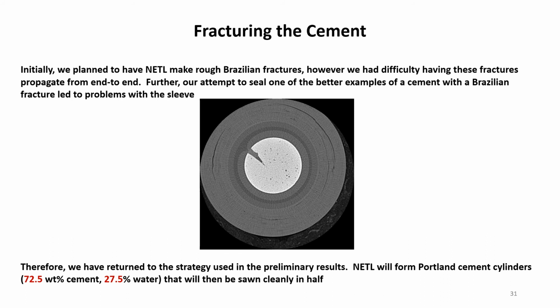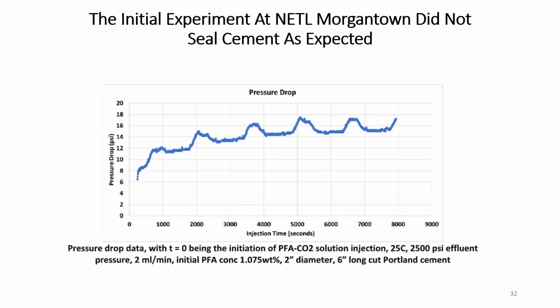As a result, we went back to the experimental setup from the preliminary results I showed earlier. However, when we did the experiment this time, the cement was not sealed as expected. There was a slight pressure drop increase, but not nearly as dramatic of a sealing effect as we were expecting.